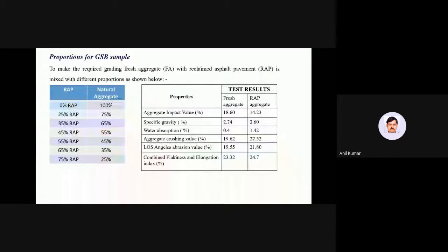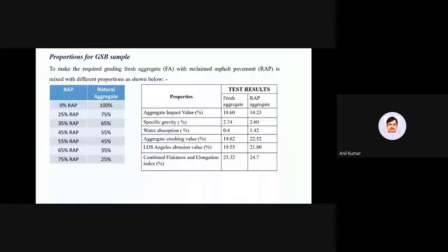The left hand side table shows the individual mechanical properties test results of RAP aggregate and fresh aggregate. Both are found suitable for construction purposes. Both are within the maximum limits, and the right hand side table shows the percentage of RAP we have used for the preparation of the GSB sample. We have used 25% RAP, increasing up to 75% RAP.